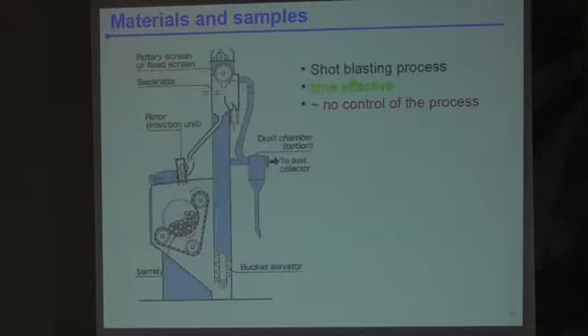Shot blasting is something which is used in the case of those components. You just put your connecting rods in a big barrel and you rotate the barrel. By rotating, and with the different contacts between the components, you improve the surface finish and you improve the fatigue properties. It's very time effective, and when you stop rolling, you get everything out, and you can do a lot in a short time. But to be honest, I think there is hardly any control of the process. It works.